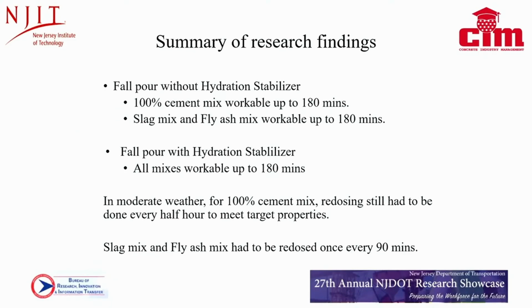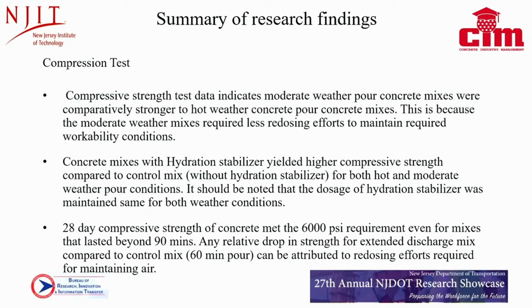During the fall, again with the cooler temperature, all the mixes had extended working times very comfortably. So again, we found that the compressive strengths for the mixes that we did during the fall were higher than the ones that we did during the summer. And we feel that is because, again, the rate of hydration was slower. So we have to retemper the mixes less. Right? We were able to meet our 6,000 psi requirement.